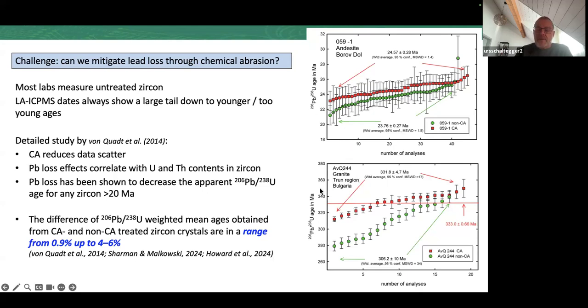And what people now do, this is another example of older, around 300 million years. So of course we take this array of data and make a weighted mean age. Even so, statistically speaking, we will not be allowed. There is excess scatter. And so the difference between the weighted mean age of the red and the green in this case would probably be several %. von Quadt et al. give a range of 0.9 up to 4 to 6% as a difference between the 2 weighted means, chemically abraded versus non-abraded.